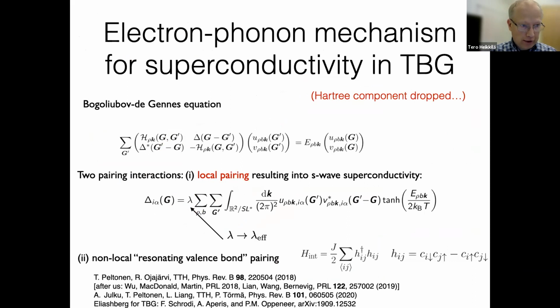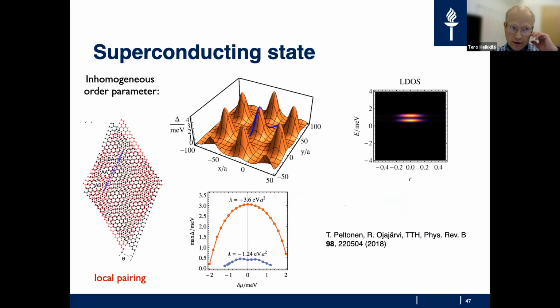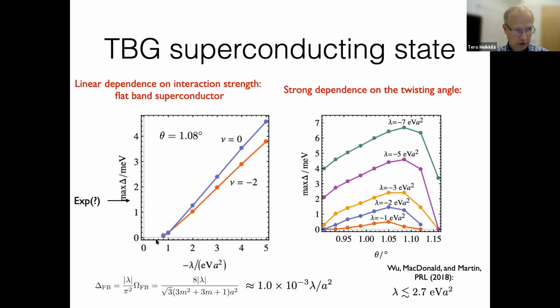Basically what we wanted was to explain these experiments. We had actually worked on this much before the experiments, but once they came, we wanted to explain them by doing the mean field here with different types of pairing schemes, and find in this system a mean field order parameter which is strongly localized, so it contains these kinds of lobes of finite delta. How large this delta is depends naturally on how large a coupling strength you put. And here is basically the picture of the delta versus coupling strength in this twisted bilayer graphene.